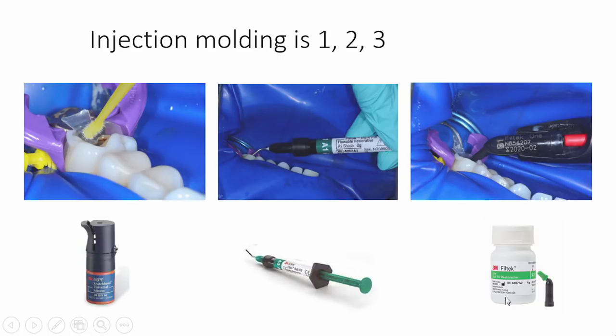And we get what we want by using these, a lot like taking a light body and heavy body impression. So once again, we massage adhesive into the dentin tubules for 20 seconds, air thin and cure, and then we inject the flowable composite. We don't cure that. And then we inject the regular paste composite, or the Filtek 1, into the bulk fill flowable, displacing it laterally. I'll show you a movie in a minute of how this works. And then we get our monolithic result.